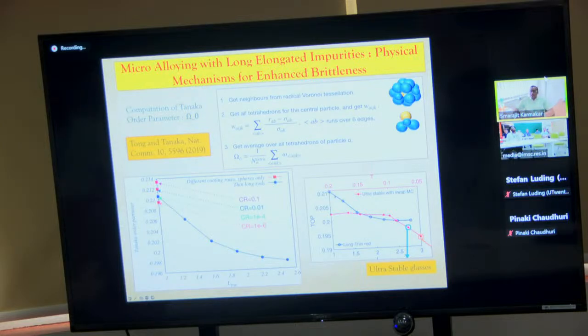So we also compared the degree of structural ordering in this, or I should not call it structural ordering, structural stability, compared to ultra-stable glasses. And it seems that these elongated rods and their concentrations can give you a glass whose stability is somewhat comparable to these ultra-stable glasses made using swap Monte Carlo. So this is an interesting way to achieve stable glasses.